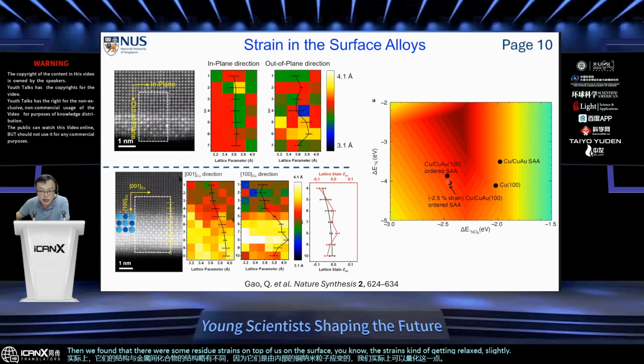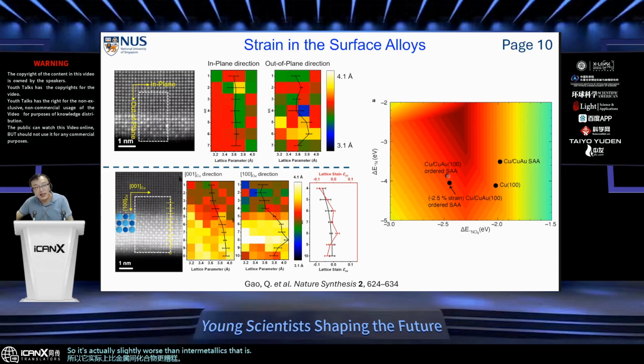And unfortunately, when we try to do the calculation, we found that this little bit of strain actually takes this adsorption energy away from the optimum. So it's actually slightly worse than intermetallics without a strain. Which also means if you can just make this layer a little bit thicker, then you will have less strain, then you should have a better performance. That is also exactly what we found later, which I didn't include in this slide.